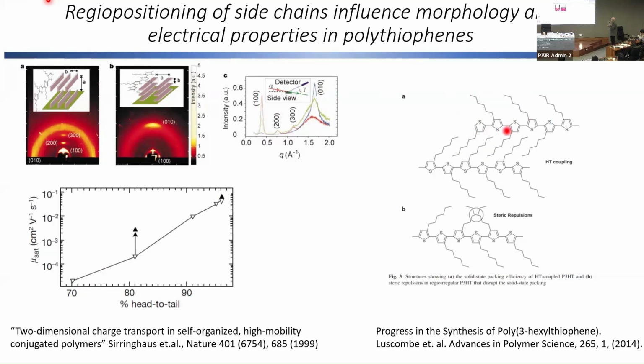But when you have these asymmetric repeat units, they introduce regioasymmetry, and that regioasymmetry can lead to disorder. And you see this in the case of this structure here. This is where we have a low regioregularity. Here, these alkyl chains are head to head with respect to each other, whereas these two alkyl chains are head to tail with respect to each other. And when you get this head-to-head coupling, you get these steric repulsions. And these steric repulsions change the thin film morphology. They change the crystallinity and they change the orientation of the backbone with respect to the thin film.